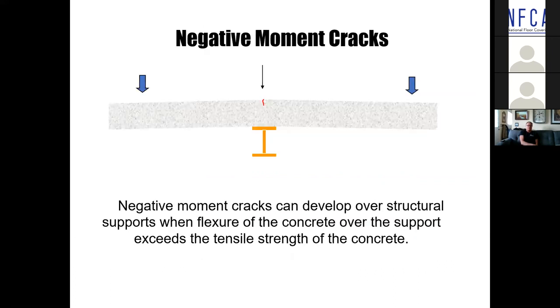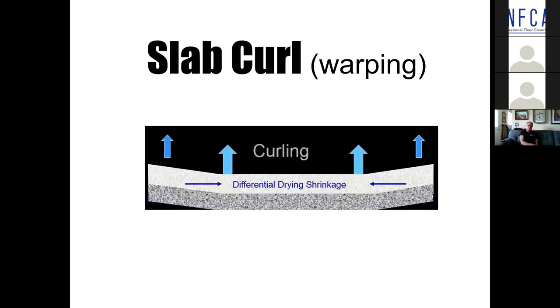And it's very common for negative moment cracks to develop on elevated slabs where there's flexure in the decking itself, and you get a fixed object like a beam or a joist, you can end up with a crack over the top of the slab. But it's important to know which type of crack you're dealing with, as I'll show you later on. Probably the biggest concern, in addition to cracking, is slab curling.